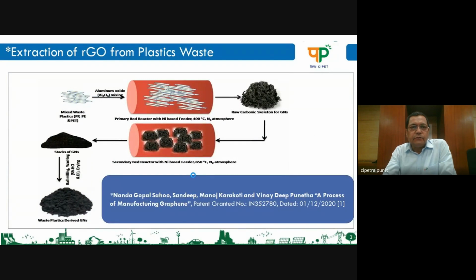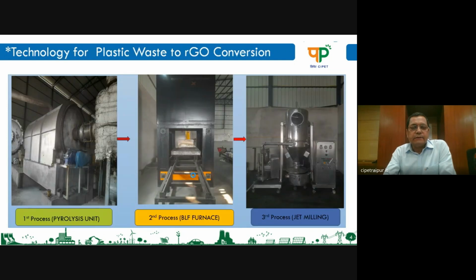And I will skip a few slides early. This is the methodology where plastic waste is converted into reduced graphene oxide. This was patented by Nanda Gopal Sahoo, Sandeep, Manoj Karakoti and Vinay Deep Punetha, and they did this with a two-process reactor: first a primary bed reactor and then a secondary bed reactor. One was at 400 degrees and another was at 850 degrees centigrade. And these GNs are now stacked, and ultimately this graphene oxide is produced. This is the methodology in a plant where they have produced RGO, and from there we have collected RGO and done various analysis.